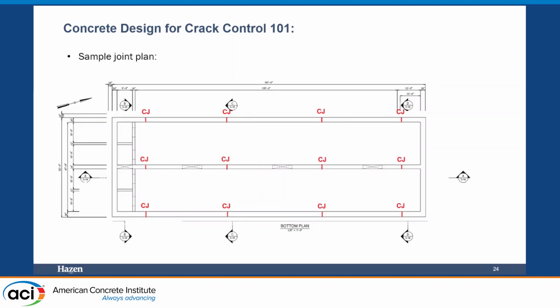Just an example here. I typically like to locate joints where the aspect ratio is around 0.75 to 1 to help control and distribute. Our goal is to get many fine cracks rather than fewer wider cracks, so that for our type structures there's less potential for leakage. For general building structures, that may produce a better finish if you're looking at an architectural wall. So joints and reinforcing are critical, I think, for helping to manage the crack.